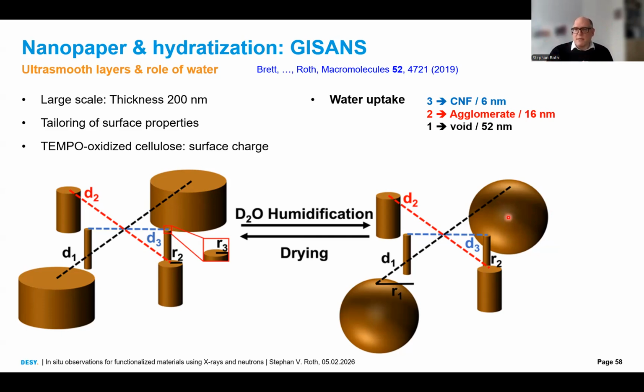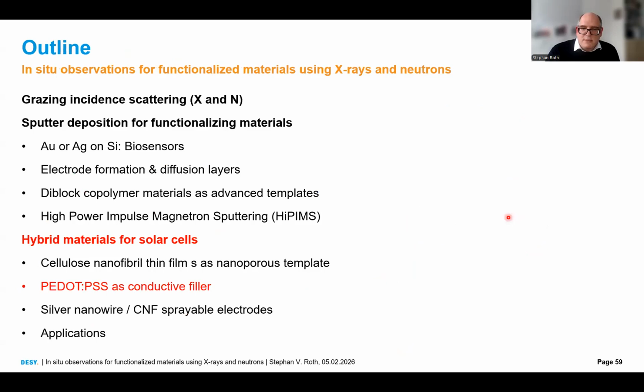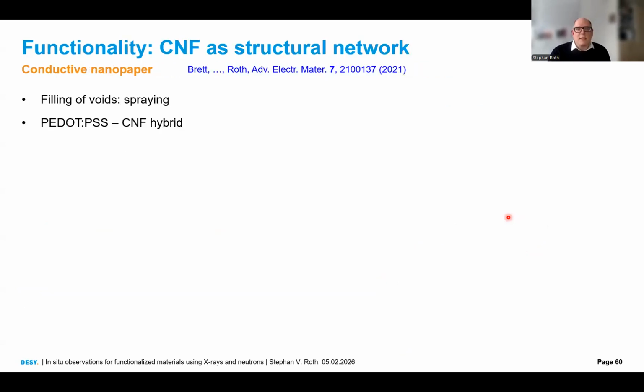And now remember what I said. We want to imbibe a functional material into exactly these voids. So you can use a water-based material to imbibe into this cellulose nanofibril structure. And this is what we then did. We used here PEDOT:PSS. This can be used as hole transport layer in solar cells. We sprayed cellulose nanofibrils and we sprayed the PEDOT:PSS. And then we looked at the hybrid structure.